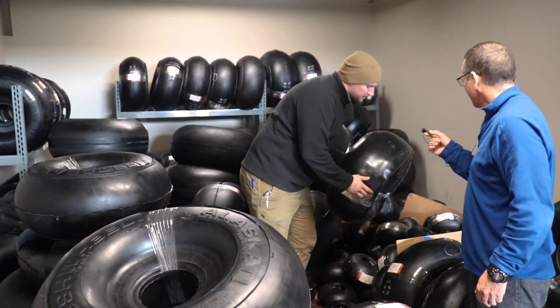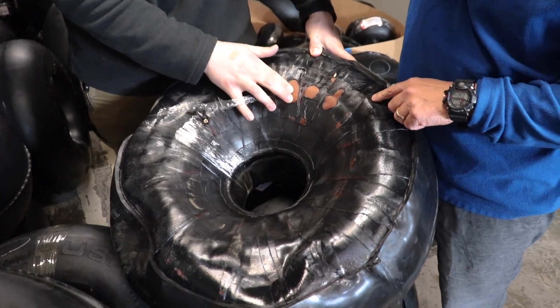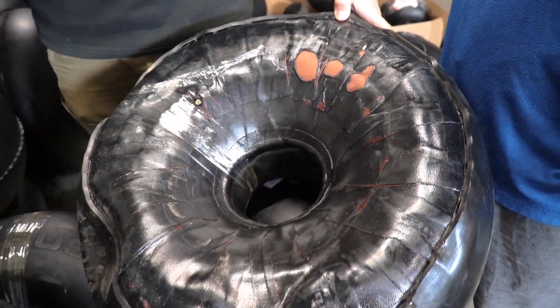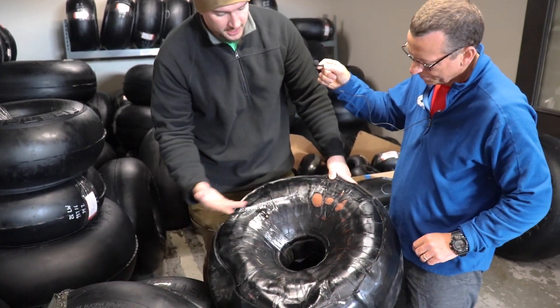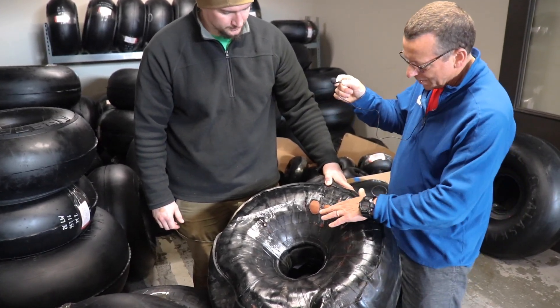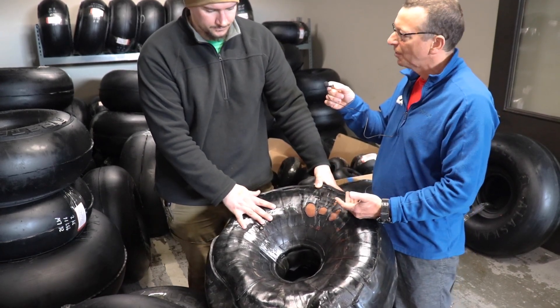This is what one of our tires looks like before it's cooked. This one had delamination on the rubber — you can see this is what some of our cording looks like before cooking. This is the nylon here, and this is a heavy tread. See how thick the tread is? When the rubber delaminates like this, it can lead to sidewall bubbles, splits, and several other issues. We recognized this early on, so we didn't even bother cooking this tire. Usually there's another ply that goes on both sides, then we dust it and cook the whole thing, but we pulled the ripcord on this one to not waste cook time. This was actually a product defect from another supplier — defective materials. So you've got an equipment failure, a process failure, and a materials failure.